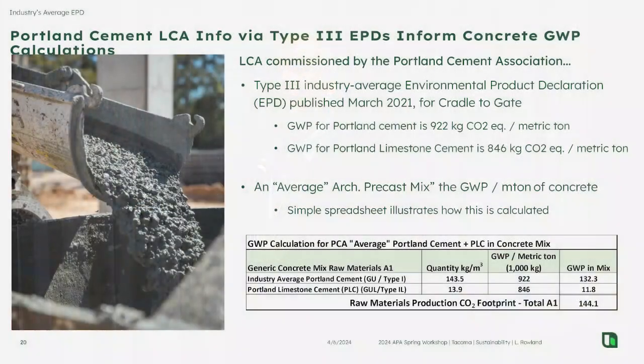I'm going to reduce that by being more energy efficient. I'm going to reduce that by utilizing alternative fuels. I'm going to reduce that by converting to Portland limestone cements and using blended cements, which reduce my clinker content. I'm going to do that by embracing supplementary cementitious materials. Remember, I said I want to get to 400 kg of CO2 associated with all the binders I sell. Well, guess what? I'm selling fly ash, I'm selling slag, I'm selling alternative binders, which have very low CO2 associated with them. That's helping me reach my goal, right? And then, of course, we want to utilize good design.